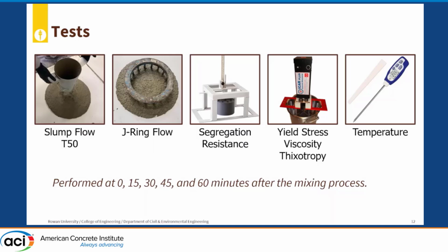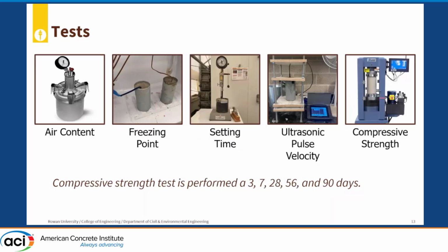We use the rheometer to determine the rheological properties. We have the yield stress, plastic viscosity, and thixotropy. We also measured temperature, and all of these tests are done at 0, 15, 30, 45, and 60 minutes after the mixing process. Other tests include air content, freezing point, and compressive strength. We also measured setting time.